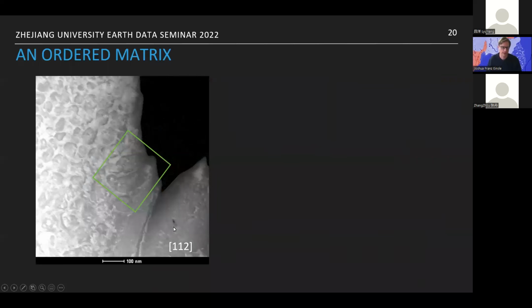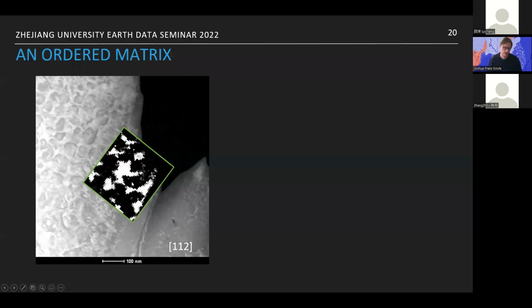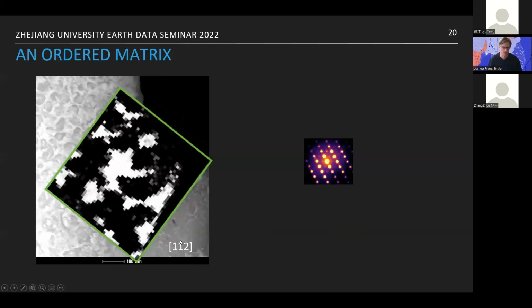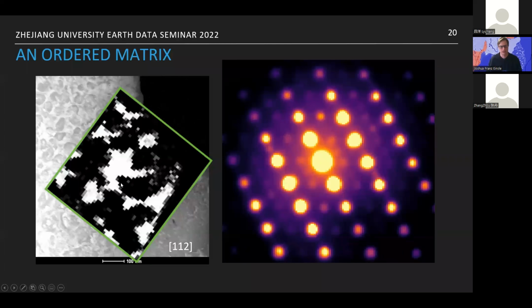So we made another lamella, and this time we looked at this seemingly strange direction, the 112 tilt direction. In that direction, the matrix, as you can see from this virtual dark field image, actually comes up very strongly. And in fact, this is the cluster loading map for the matrix, where we have now recovered this very strange, very difficult to interpret diffraction pattern, which looks at first glance like an FCC type material, but with these forbidden reflections up here.